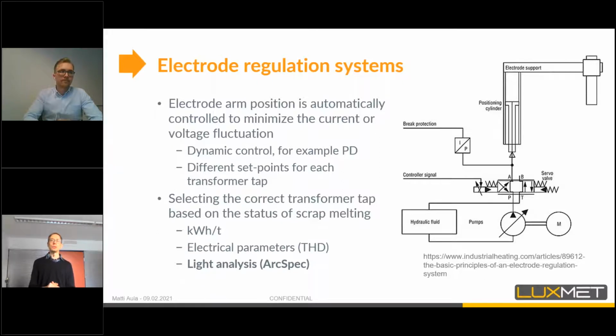And then the furnace also utilizes this long-term or mid-term control, which is the transformer tap control. So what is the correct transformer tap to use in this phase of the process? Normally furnaces have a tap profile which they use. Usually there is some set profile with kilowatt hours per ton, but usually these kilowatt hours per ton should also be modified according to scrap melting. So you have a certain assumption of the scrap melting which you modify with dynamic information about the scrap. And in this scrap melting, you can use our systems to time the voltage ramp, so that when you know that these electrode hotspots are exposed, you know what things to do.